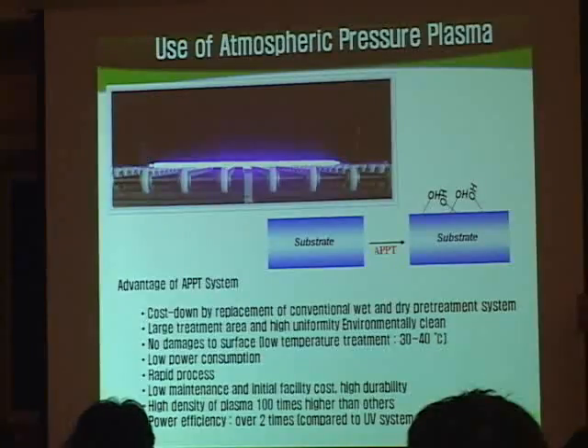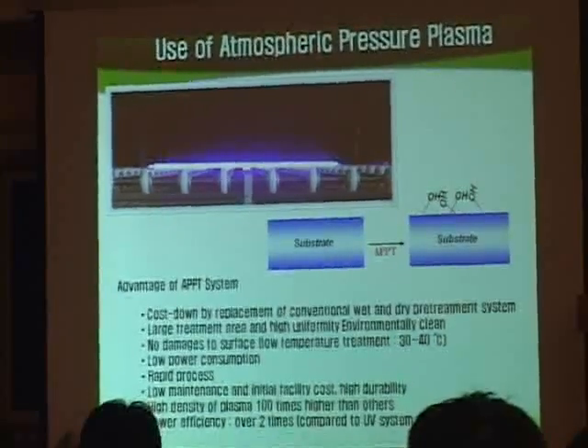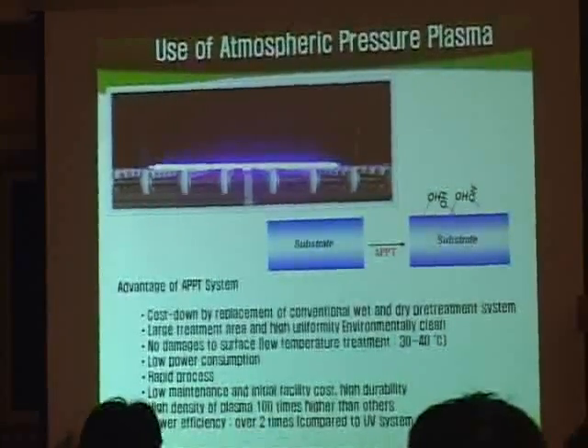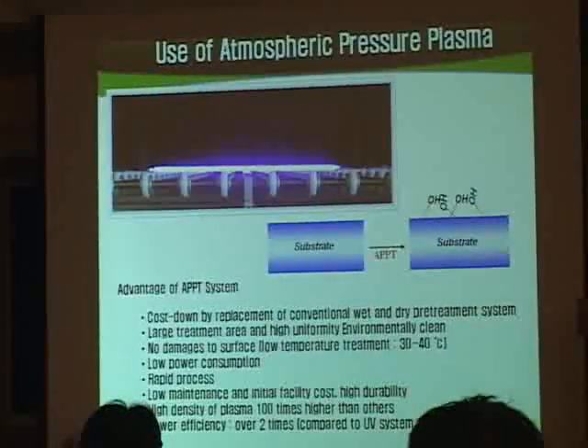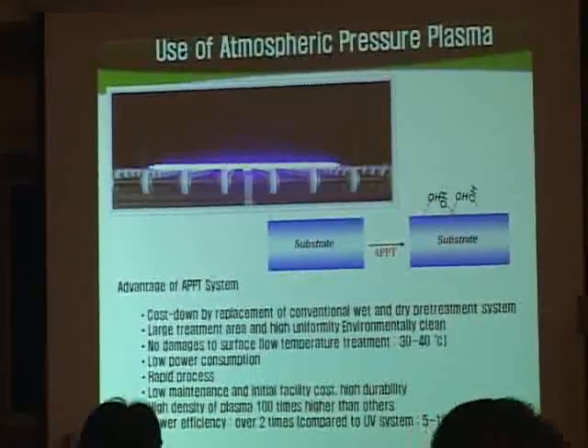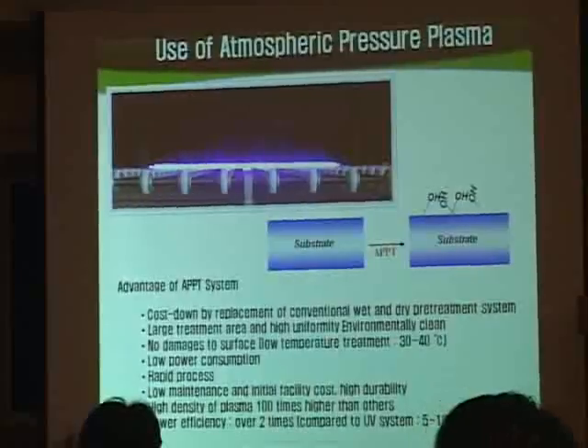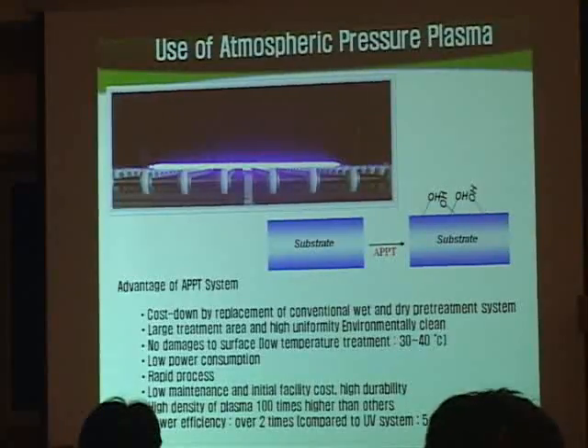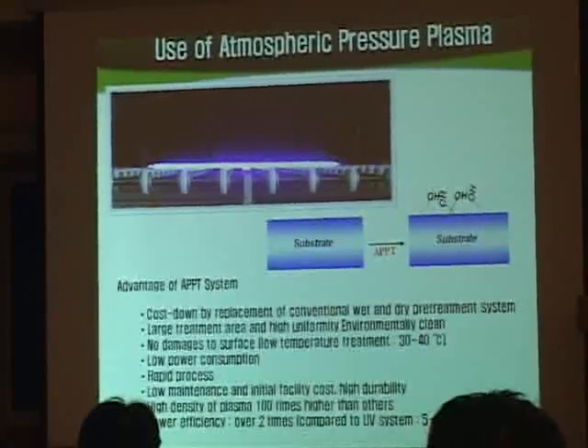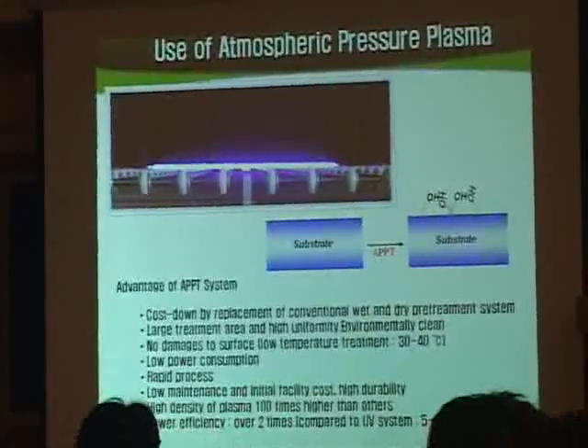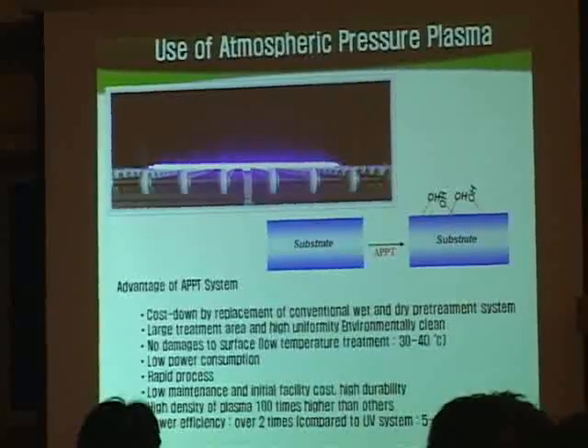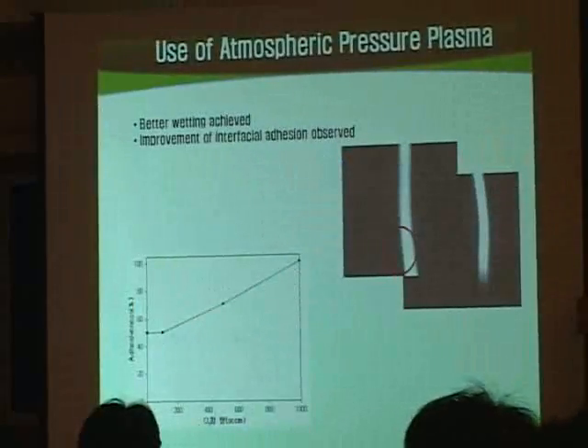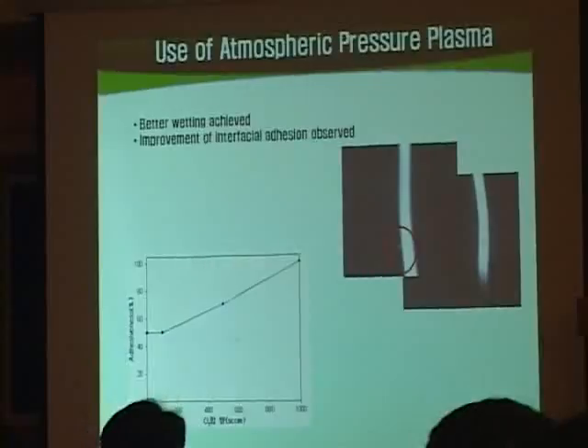Instead, we want to only enhance this reactivity to incoming coating. So we realize this kind of process gives us freedom to utilize atmospheric pressure. We don't have to put this film in the vacuum chamber for the certain plasma treatment, and then we realize that this treatment is very effective, so cheap.